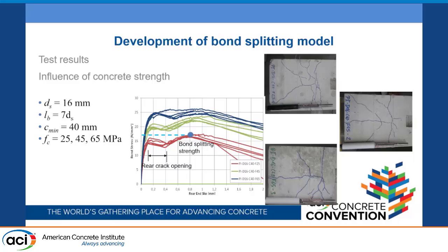But once the crack intercepts the reinforcement, then the crack is stopped and the load is again taken up by the rebar. Eventually it fails in concrete splitting. So what we see here, as expected, with increasing concrete strength, even though your bond strength is not increasing, you have higher splitting strength because it's a concrete tension failure mode.